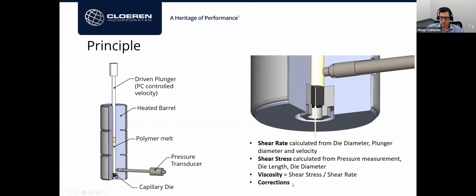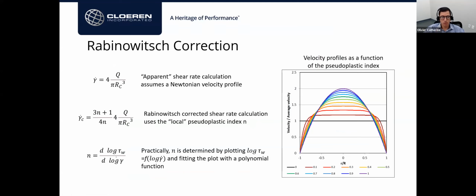However, there are some corrections necessary to get to the most precise, most meaningful measurement. The first correction is the so-called Rabinowitsch correction. When we calculate shear rate, we apply, again, simplified equations that assume the material is Newtonian. The equation only uses the flow rate of the material and the radius or the diameter of the capillary. But as we are dealing with non-Newtonian materials, the velocity profiles change as the material flows through the capillary, as shown in this graph here.